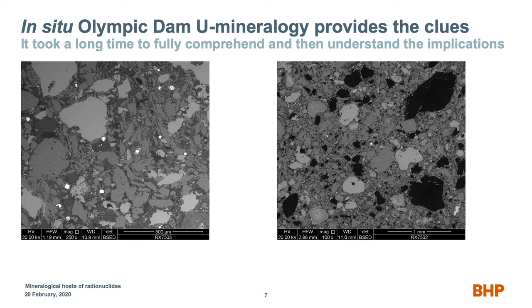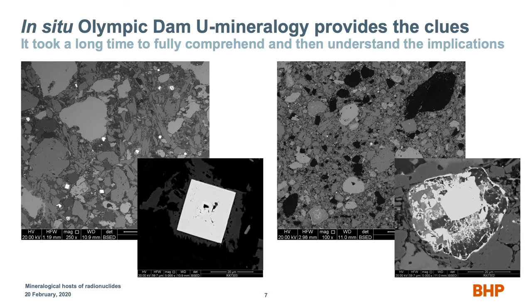And over here, the scale bar is a little bit different, but the same kind of texture. It's a breccia, and a few bright spots around, and that's uranium. And those bright spots are only about 20 microns in size. So we zoom into these things, and in a modern sense, we're actually able to see and image these things, like 20 microns in size, beautiful little cubic grains, and we have all kinds of those. And these are really important ones.